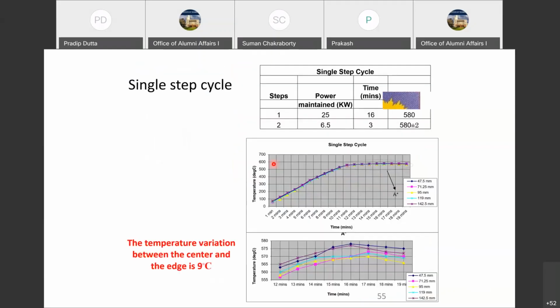So as we see here, suppose we do the reheating in a single step cycle all the way to the semi-solid temperature, which is nearly about 583 degrees. If we expand this, we see between the center and the edge there is a large temperature difference, nearly about 9 degrees, which is not acceptable, because you need the entire billet to be at the same temperature.